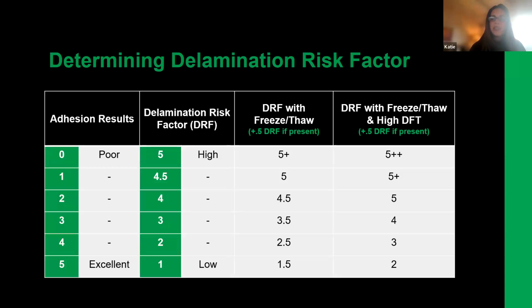So first, let's look at the adhesion results. In this case, a cross-cut adhesion result that we see in column 1 right here. 0 rating is poor, so that's easy to see here. 5 is excellent, also easy to see here. So the delamination risk factor is actually the direct inverse of the adhesion result. So that kind of makes sense too.